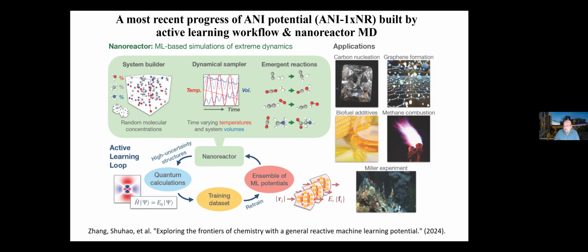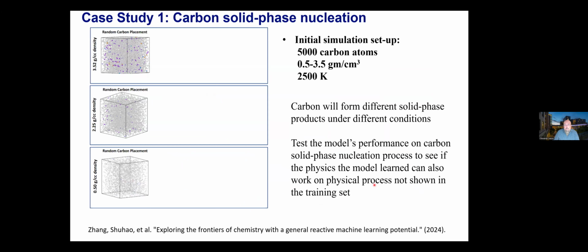I'll show you a couple of applications, but in the paper we actually had to do and show five: nucleation of carbon, formation of graphene, various types of combustion applications, and early life, for example, like the Urey-Miller experiment. So one example, we were very surprised that despite the fact that the potential was trained for small organic molecules and maybe a little bit larger clusters of atoms in the training, we were able to reproduce a decently good phase diagram for carbon.